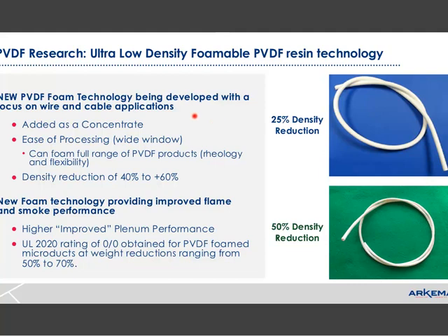be difficult. Well, there are new developments going on with foaming technology that eliminate these process-related problems that affect startup and increase scrap rate. And not only that, but they are able to get foam reductions of 65, 70% very consistently. And it's controlled simply by the addition of the concentrate, independent of processing conditions. What's exciting about some of these new technologies is that we're seeing extremely good plenum performance.